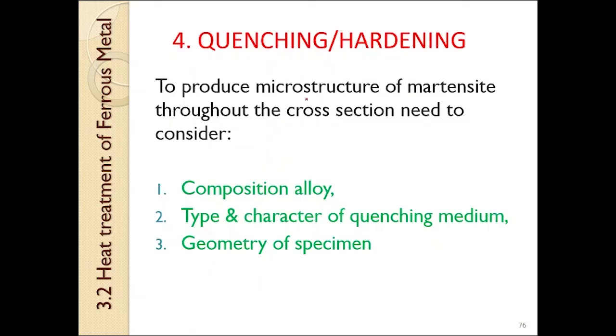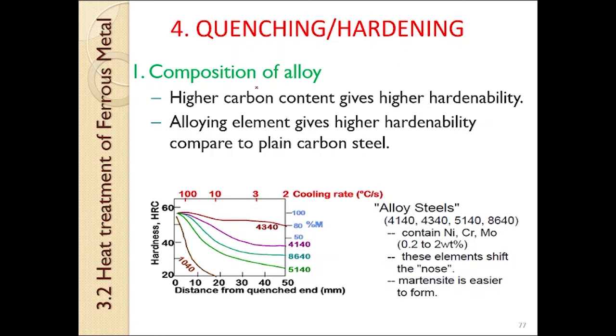To produce a microstructure of martensite throughout the cross section, we need to consider the following. The first one is the composition of the alloy, the second is the type and character of the quenching medium, and the third is the geometry of the specimen. For composition of alloy, higher carbon content gives higher hardenability. Alloying elements give higher hardenability compared to plain carbon steel.